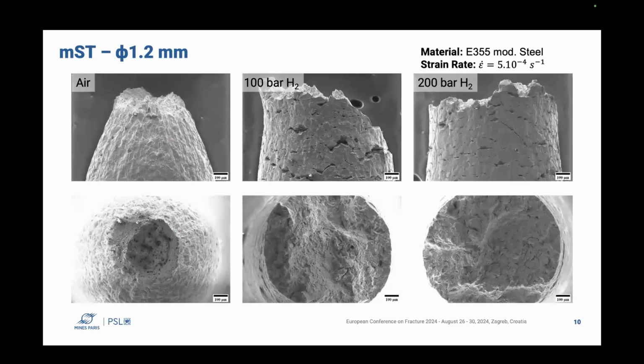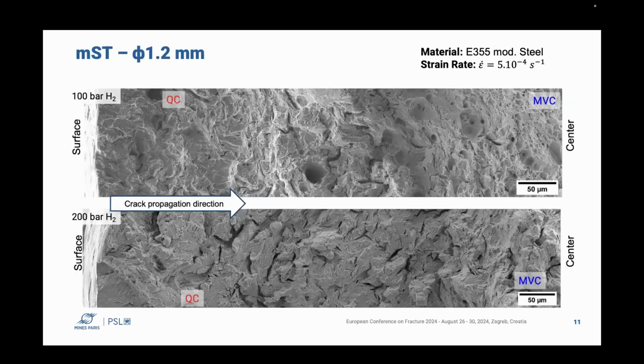So here I show the fracture surface. In air, we have the typical ductile fracture I would expect. And we can see several differences at 100 bar and 200 bar. For 100 bar, we can see at the surface 100% quasi cleavage, and there is a smooth transition onto the center, where we can see the microvoid coalescence feature. But those dimples that we observe here are smaller than the dimples we observe in air.